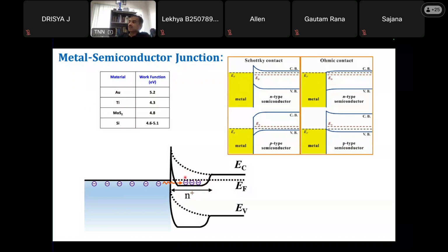So basically, what you mean by degenerate semiconductor with a heavily doped junction is that you are bringing down the tunneling barrier, so that tunneling will be easier and you can ensure a flat band near the metal semiconductor junction. Then you can have a very feasible electron transfer from the metal to the semiconductor. This is the way the bulk semiconductor industry works, making a very nice contact between the metal and semiconductor to address the Schottky barrier junction.